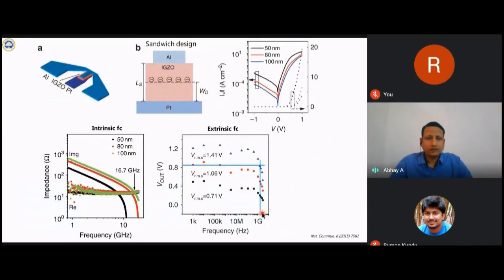To tell you a little bit more about the device geometry, this is work published by UK researchers in 2015, where they made a Schottky diode between indium gallium zinc oxide and platinum as a metal electrode. You can see it is a vertical diode, and this design is called a sandwich design. The top electrode is aluminum, then this is semiconducting IGZO, and platinum is the second electrode. When the voltage is applied, current flows in a vertical direction. This is the DC characteristics, plotted for different thicknesses of IGZO.